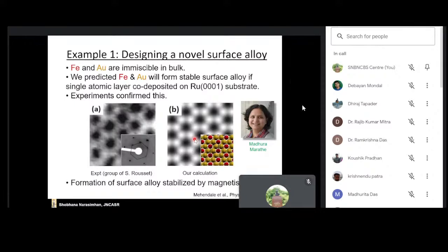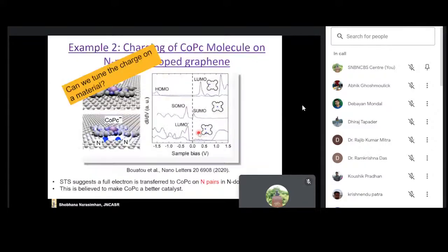In other words, if we turned off magnetism, this alloy does not form, but if you turn it on, it forms. So the reason it forms is that when you form this structure, every iron atom, which is surrounded by 6 gold atoms, acquires a very high magnetic moment, and the resulting exchange energy stabilizes the whole system, and that is why this alloy forms.